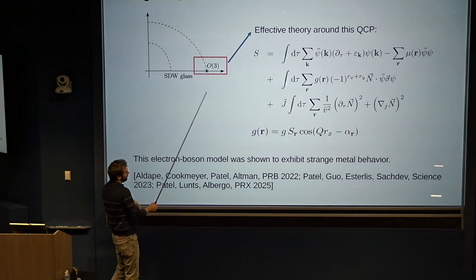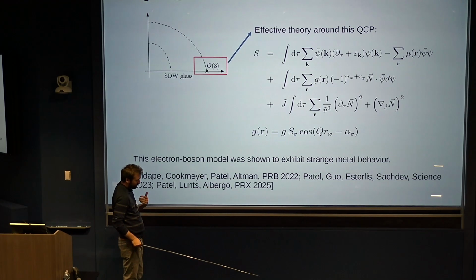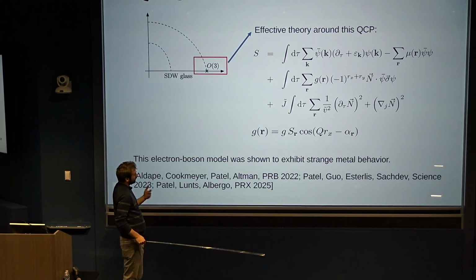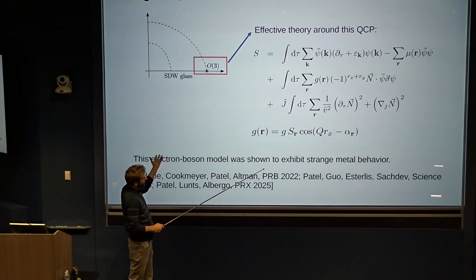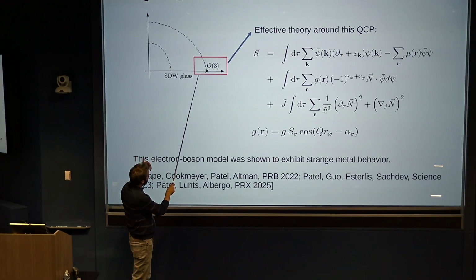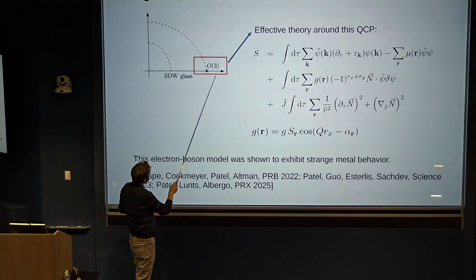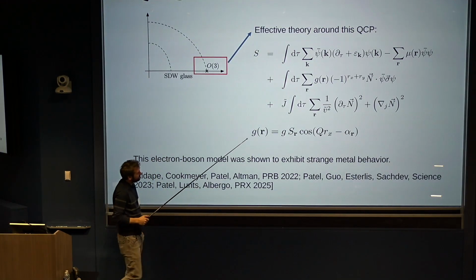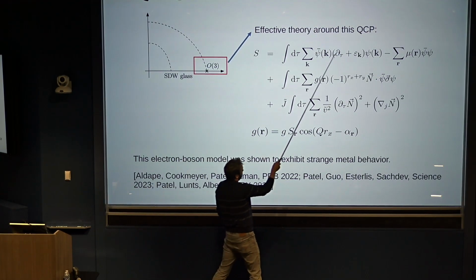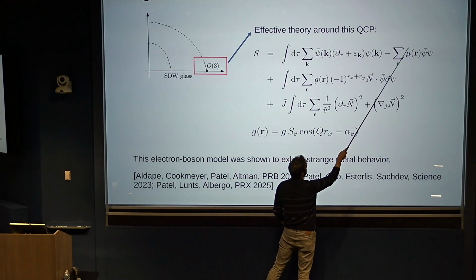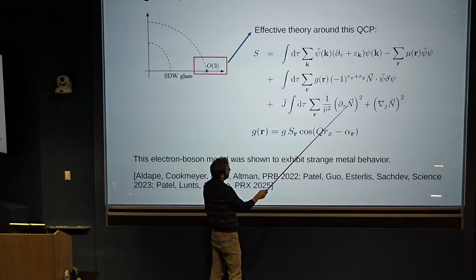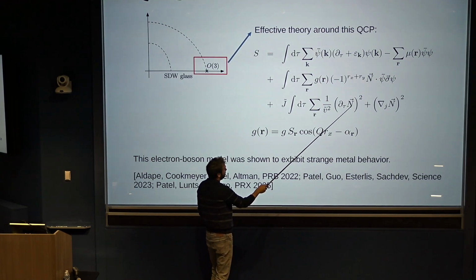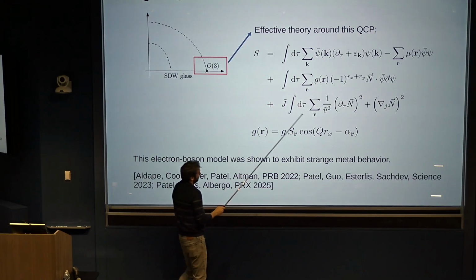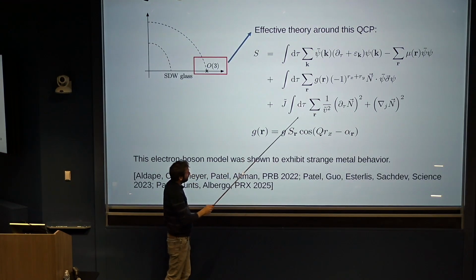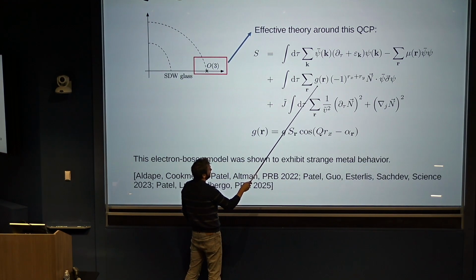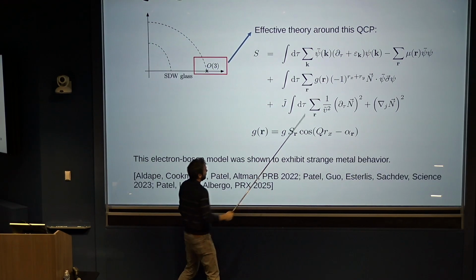If you take your Landau-Ginzburg theory and couple it to fermions, so you promote it to a Landau-Ginzburg-Hertz-Millis theory, then if you put in the disorder, you can derive by a few simple steps the effective theory for this O3 transition. You find it's of this form, and it's deceptively simple. There's a free fermion term, so there's some potential disorder for the fermions. Then there's this field which describes the spin fluctuations. This is the field which becomes critical here at the O3 transition. And then there's a Yukawa coupling between the two. But importantly, the coupling constant now varies from point to point. And it takes on this form.